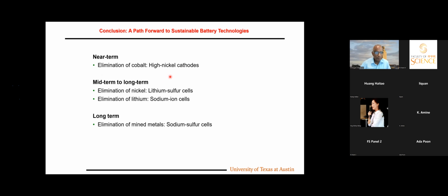Mid-term to long-term, elimination of nickel, and that is lithium-sulfur. Long way to go, a little bit. Right now, there are companies who are making cells. They are limited in cycle life, maybe 150 cycles or 200 cycles with fairly reasonable energy density, 300 watt-hour per kilogram or 350, around that. So it is just getting there. Only 10 years, very much work has been done.